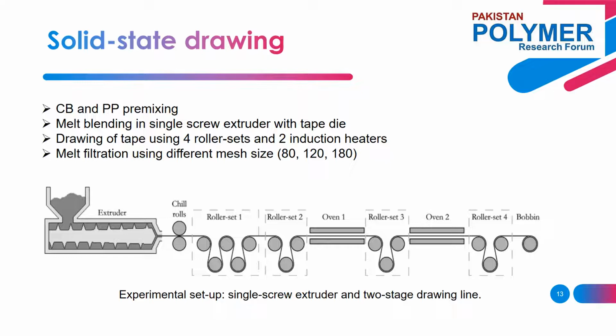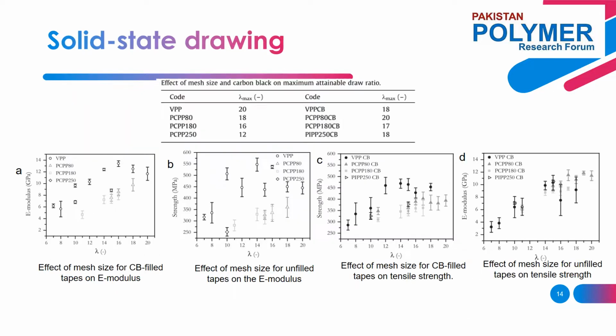The tapes were quenched with chilled rolls, and a drawing line with 4 controllable induction heated roller sets and 2 induction heated ovens was used. The oriented tapes were wound onto a bobbin and used for further characterization. The effect of mesh size and carbon black is presented in the table. It can be observed that for virgin PP, the addition of carbon black results in a reduced draw ratio. With the addition of carbon black, the maximum attainable draw ratio is lower since it acts as a contaminant.